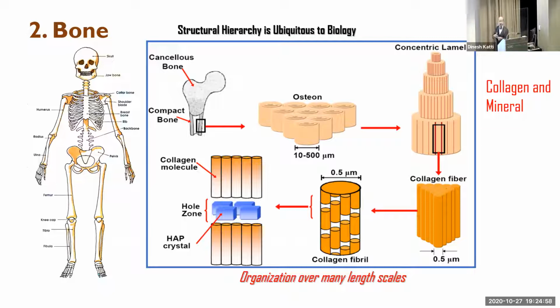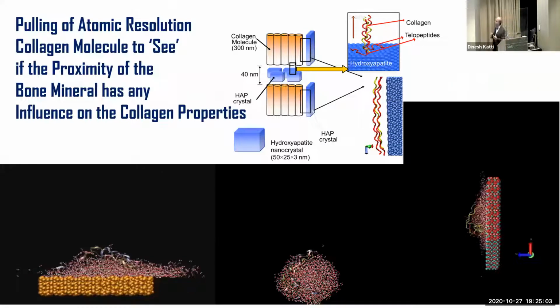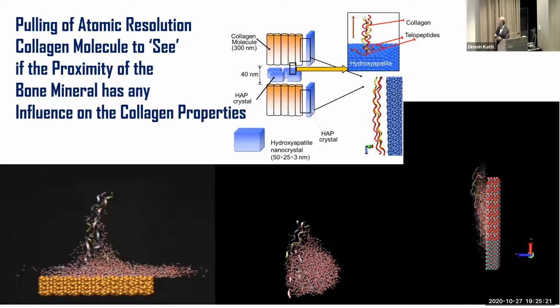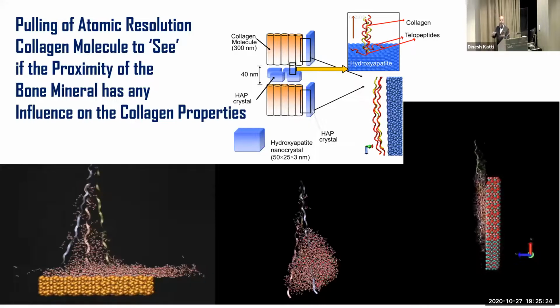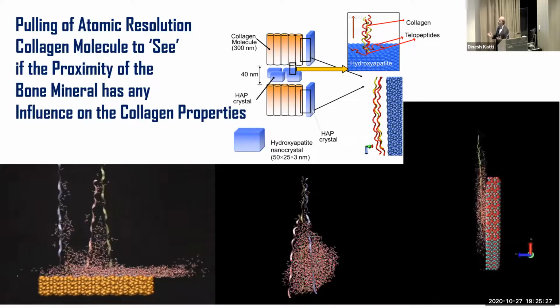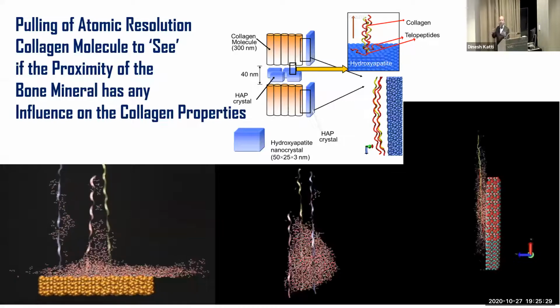And so what we did was we pulled the collagen to see if the proximity of the bone mineral has any influence on the collagen properties. So basically what we did was we took the collagen and put it next to the mineral in all these different orientations which you see in the bone. And then we also compared that with the collagen without the proximity of the mineral. And we did that, and these are the results.